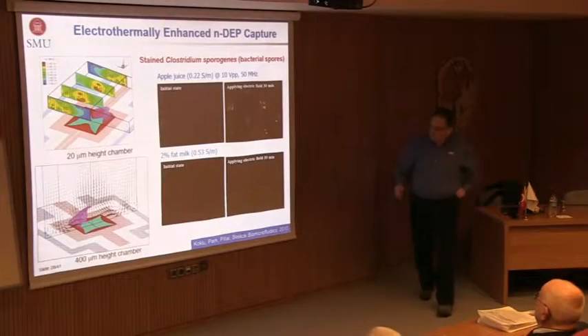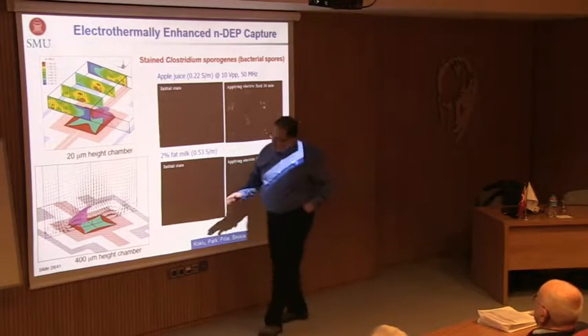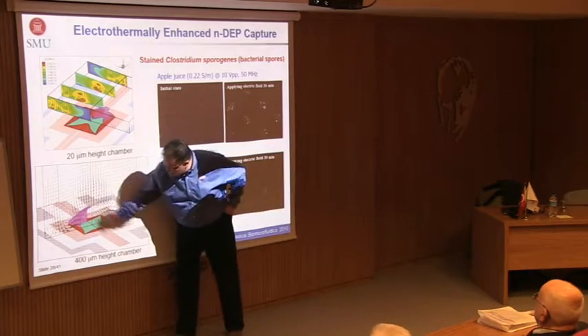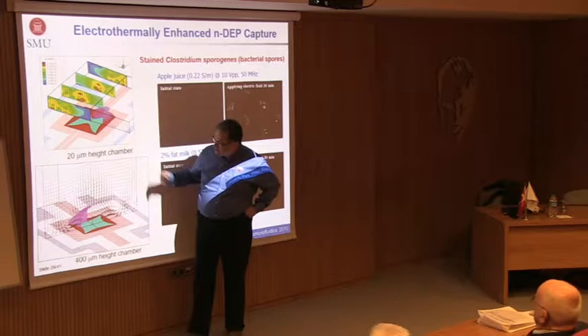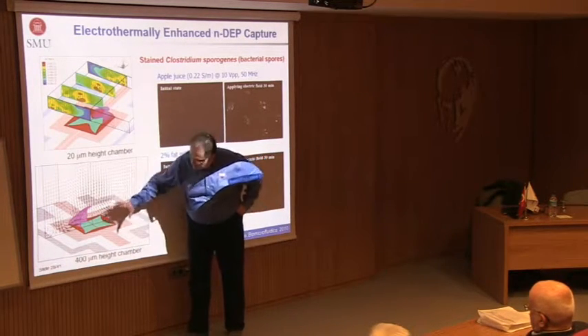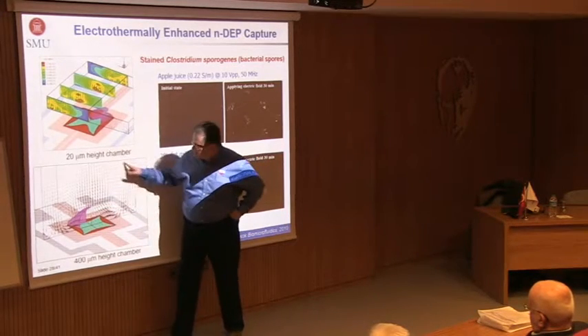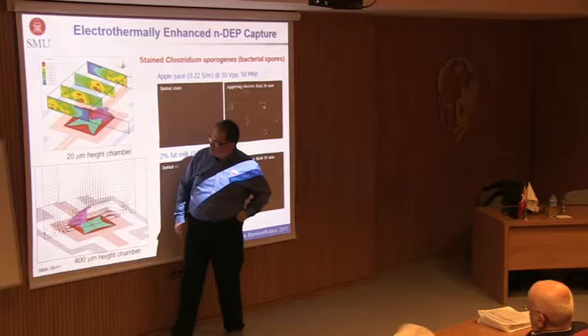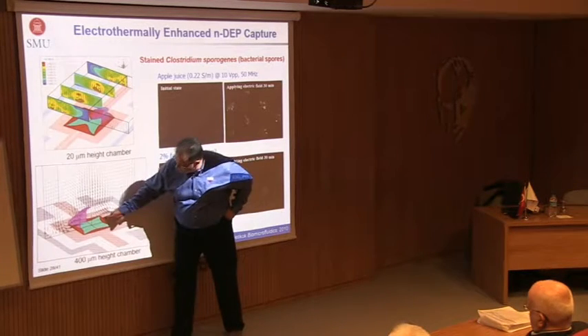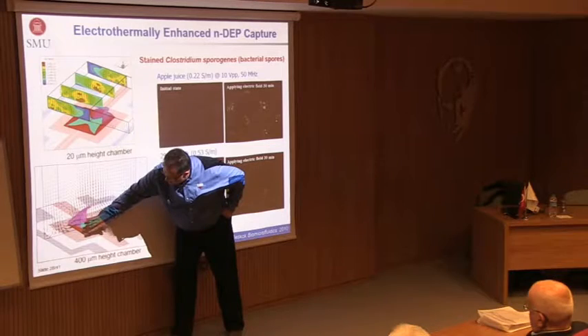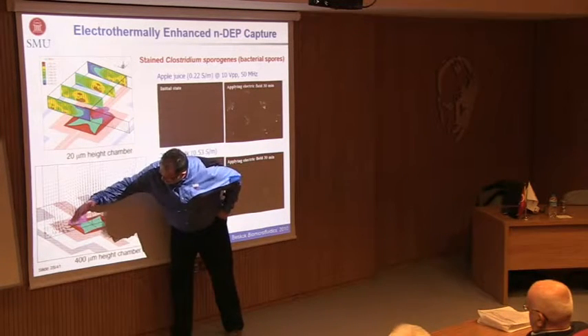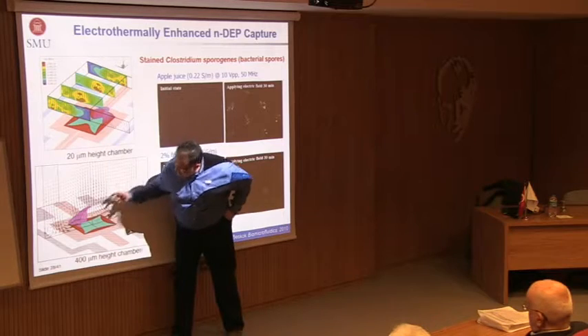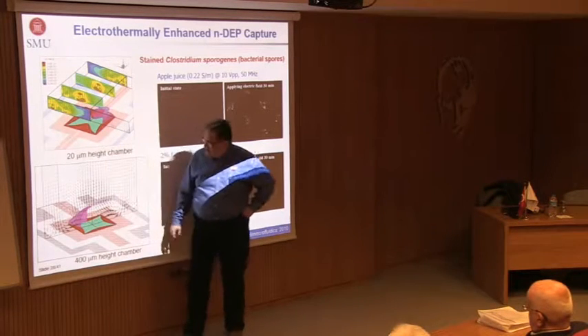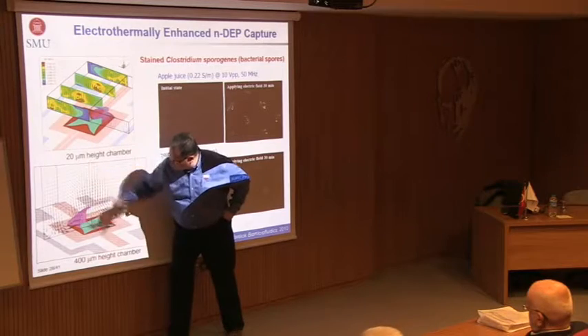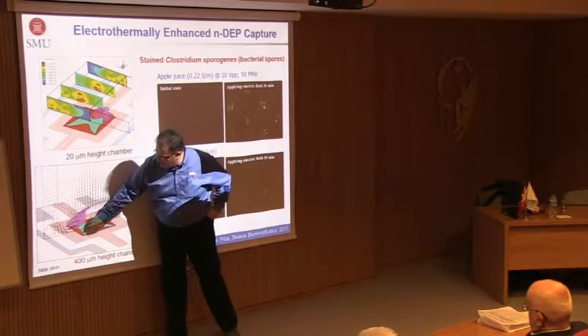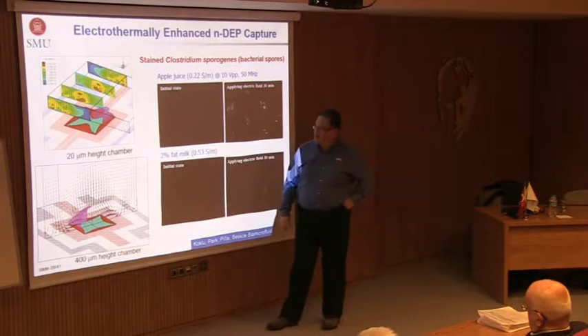So what we did is we tried to simulate that, and depending on the height of the chamber that you have, these are our square electrodes, you actually can create flows in these periodic structures, in the sense that you can have circulating loops like that. Assume that particles are brought in, and this is my electric field minima, and I created a dome, and under the dome, everything is going to basically go there and stay there. And of course, there is a possible lift, but if the gravity also helps you, you may be able to concentrate particles right in the middle.